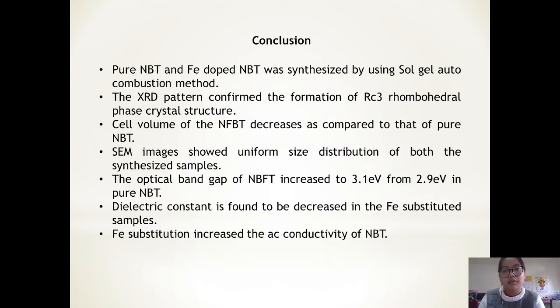So from the above results, we can conclude that pure NBT and iron-doped NBT were synthesized by using sol-gel autocombustion method. The XRD pattern confirmed the formation of R3c rhombohedral phase crystal structure. Cell volume of the NBFT decreases as compared to that of pure NBT. SEM images showed uniform size distribution of both the synthesized samples.